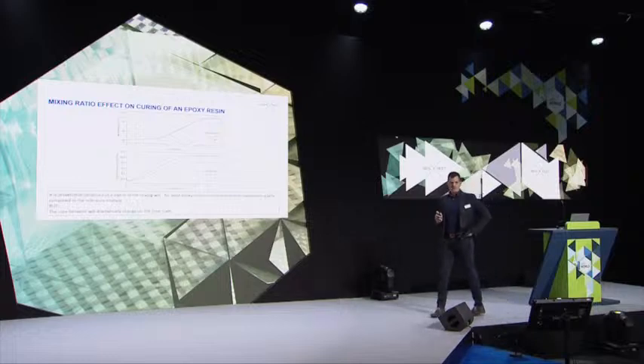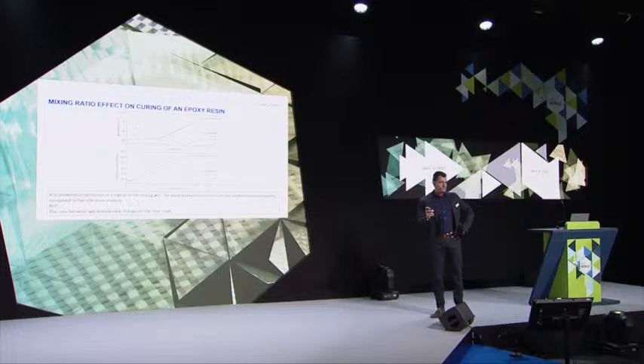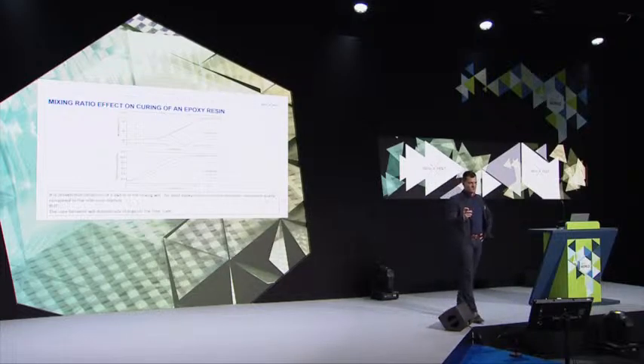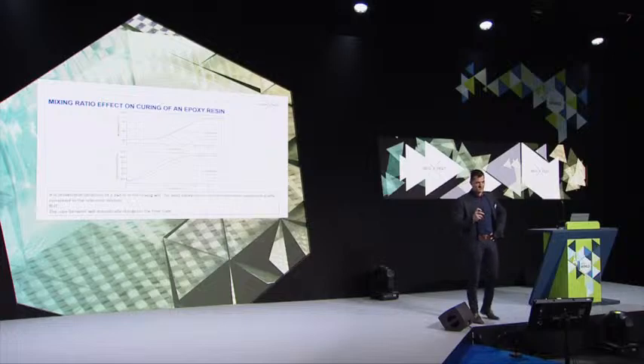The next picture, mixing ratio effects. For most of the epoxy resins that are out there today, it's already proven that a mixing ratio of plus minus 2% in the hardener content results in the same mechanical performance. So I have an interval from minus 2% up to plus 2% in the mixing ratio compared to the ideal state, and I get the same mechanical performance of my components.